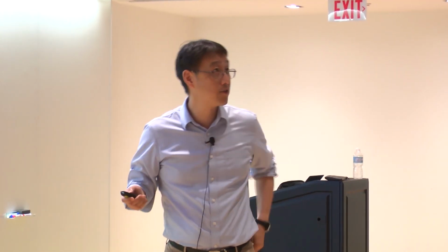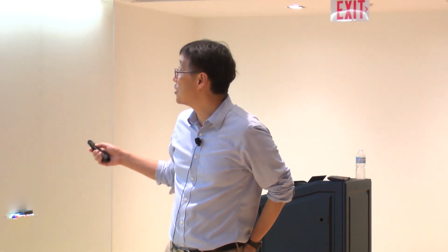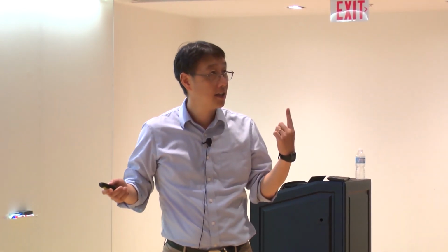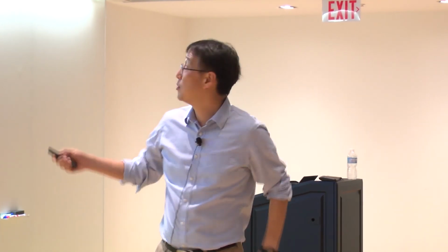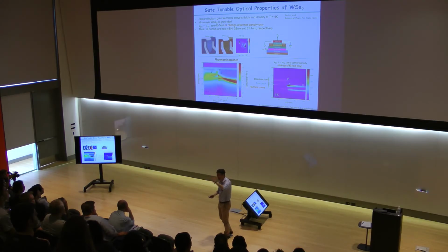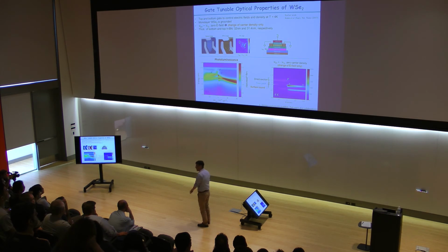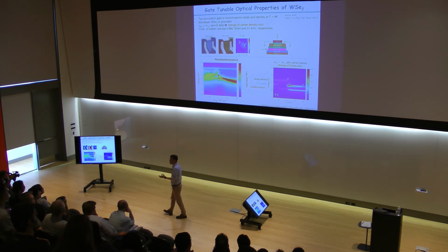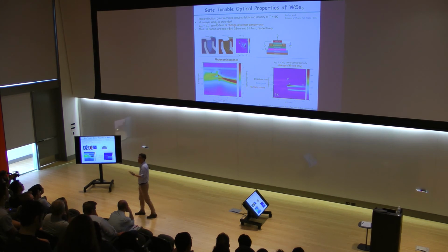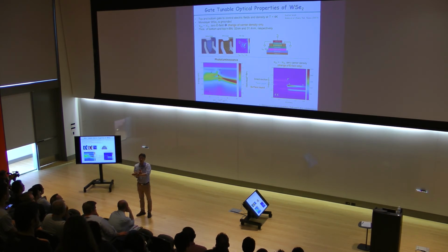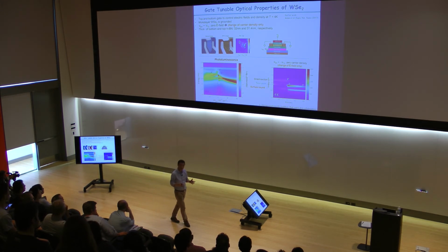But the important part is this exciton we create, or trion we create, in a two-dimensional system. As a function of the electric field in the vertical direction, the intensity got modulated, but what you see in the energy position is that it's just constant, right? And this tells us that whatever dipole moment this species, excitons or trion, we create has, this dipole moment should be in plane, such that it's orthogonal to the electric field we applied in the vertical direction. Another way to say that is, it's a truly two-dimensional object we can create optically, and potentially we can also electrically manipulate it, right?